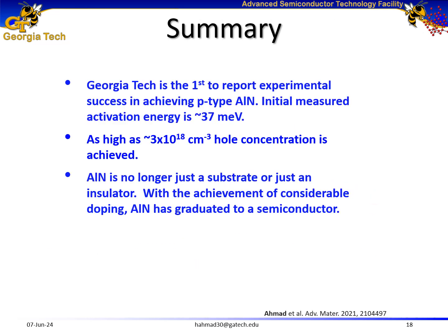To summarize the key results, we at Georgia Tech are the first experimental group to report success in achieving P-type aluminum nitride films with a very low activation energy of 37 milli-electron volts. We have achieved as high as 3 into 10 to the power of 18 per centimeter cube hole concentrations. And we believe that with this achievement, aluminum nitride is no longer just an insulator or substrate. It has graduated to a semiconductor.